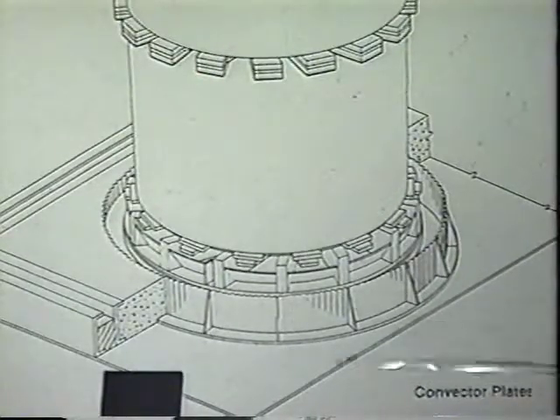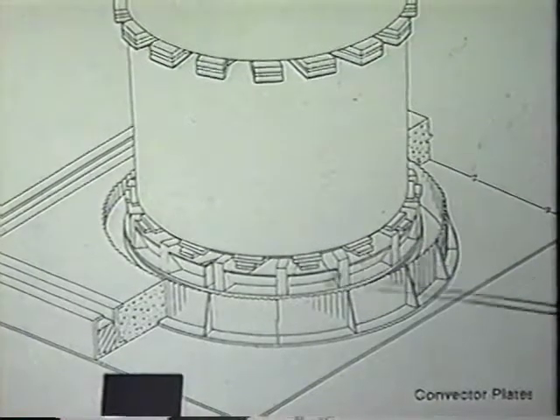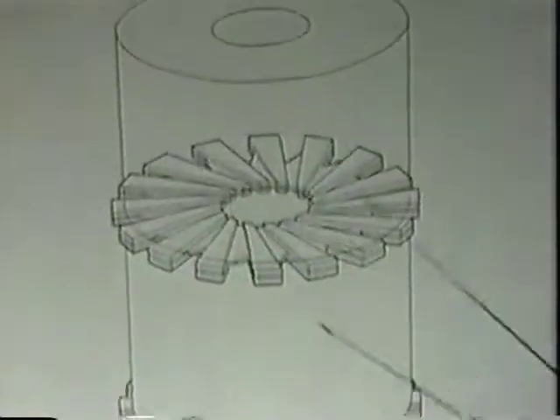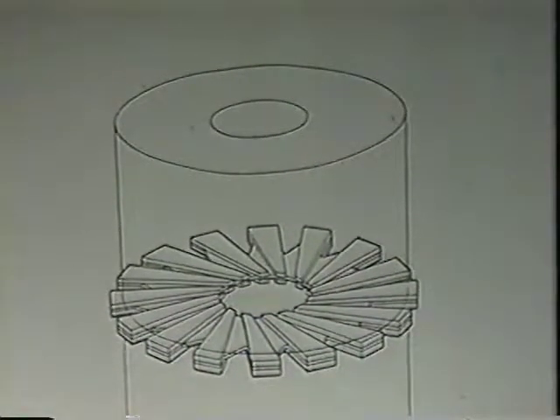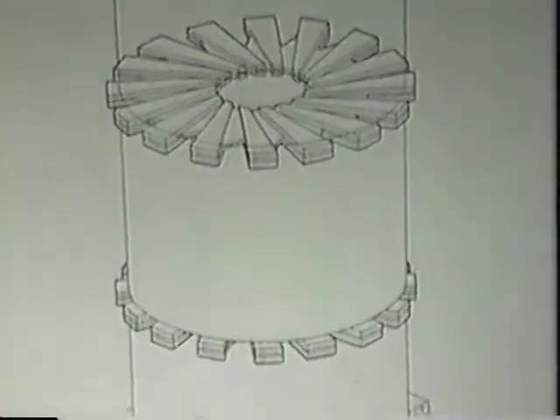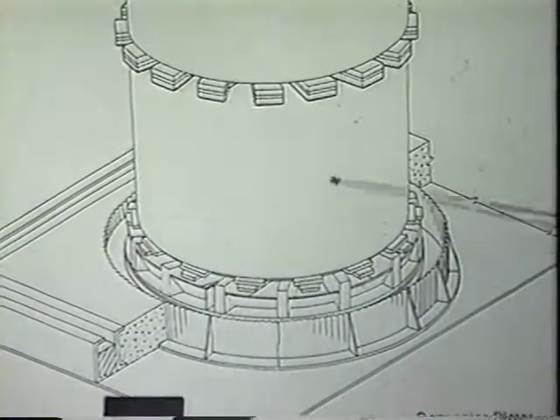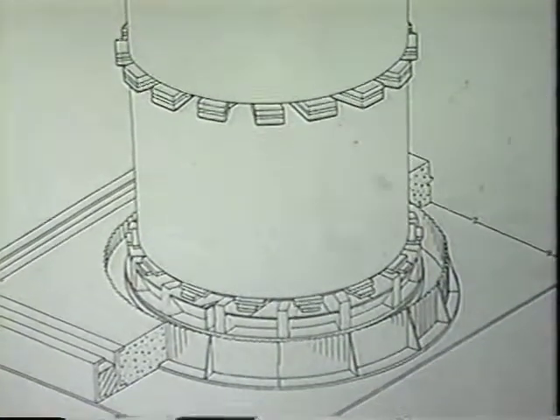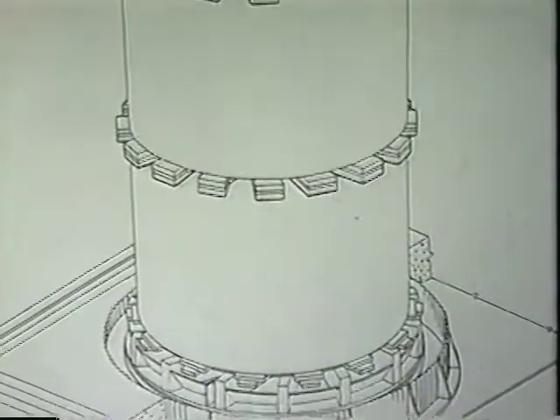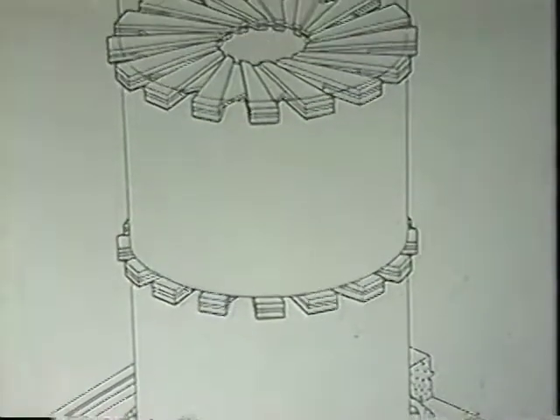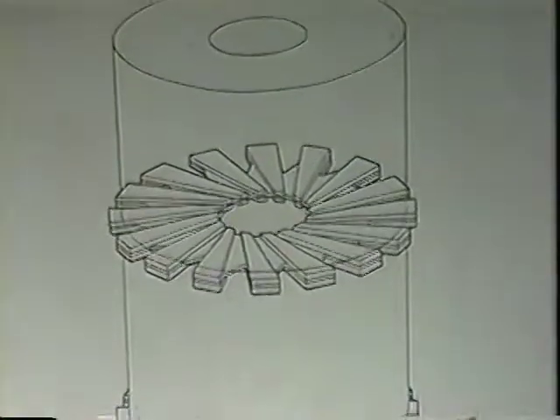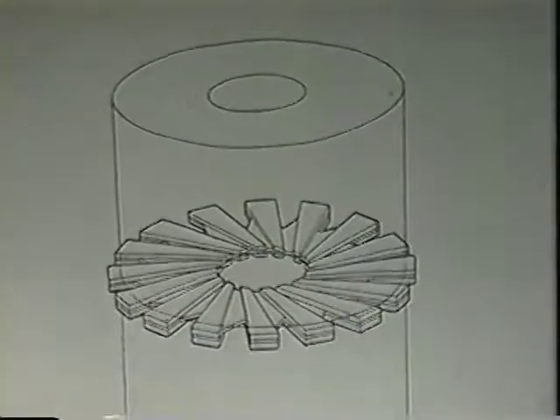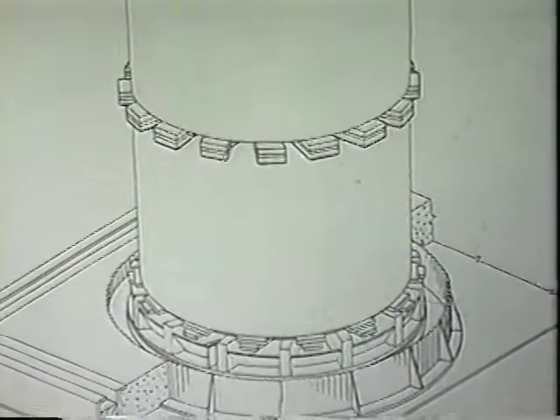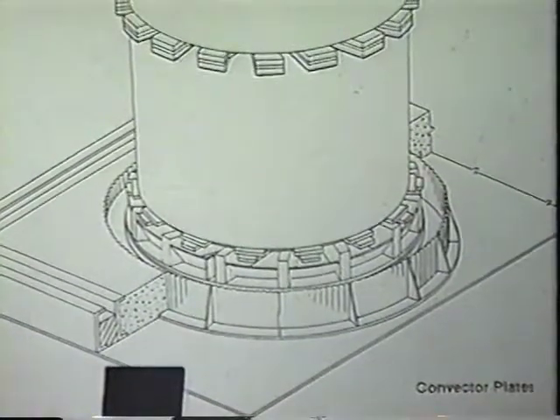But when you go into the anneal facility, you'll see what looks like a bunch of small little grain silos. Those are nothing more than stacks of coils with covers on them. Inside the cover, you can see there would be 3, 4 coils stacked up on top of each other, sometimes 2 if they're real wide. At the bottom of the anneal stack is a pedestal with a fan in it. Between each coil, we have convector plates, which add a little air gap. Okay? The intent here is to circulate air through the eyes of the coil, down the aisles, out between, and then back up around the stack. So it's a continual flow of atmosphere around, heating the coil.